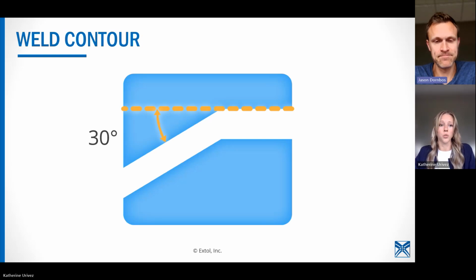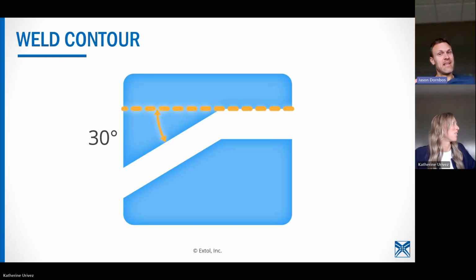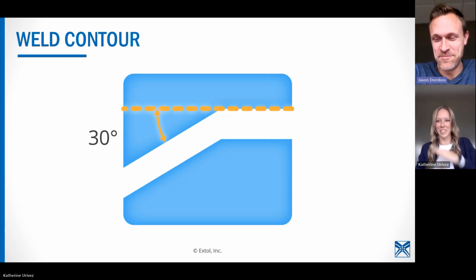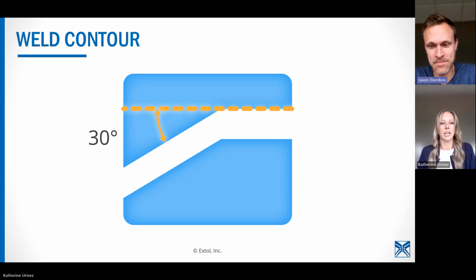And then weld contours. This was also a question I think came up in the registration. What does it look like to weld something that maybe has multiple planes? We recommend 30 degrees is the minimum weld contour. The maximum. Add anything over 30 degrees, we want to see only 90 degrees. Just kidding. Please don't do that. 30 degrees is the maximum. I almost did it again. The maximum angle we want to see in the part geometry.